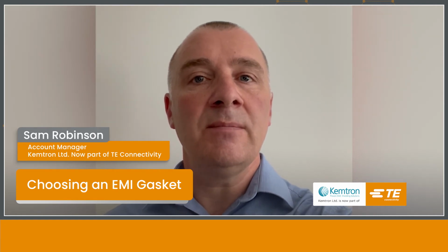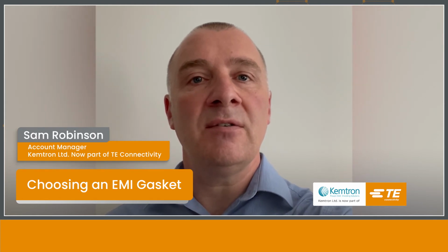When two different metals are in contact with each other, in the presence of moisture, or more so in salt spray, galvanic corrosion will occur. It is therefore important to try and match as closely as possible the conductive gasket metal to the enclosure metal on the galvanic scale. For example, a nickel-coated, plated or painted enclosure in contact with a nickel-coated graphite in silicone elastomer gasket will be a perfect match. However, at the other end of the scale, a silver or copper-based gasket in contact with aluminium in a salt spray environment, corrosion will rapidly take place, causing a breakdown in the conductive joint as the potential difference between the materials is great.